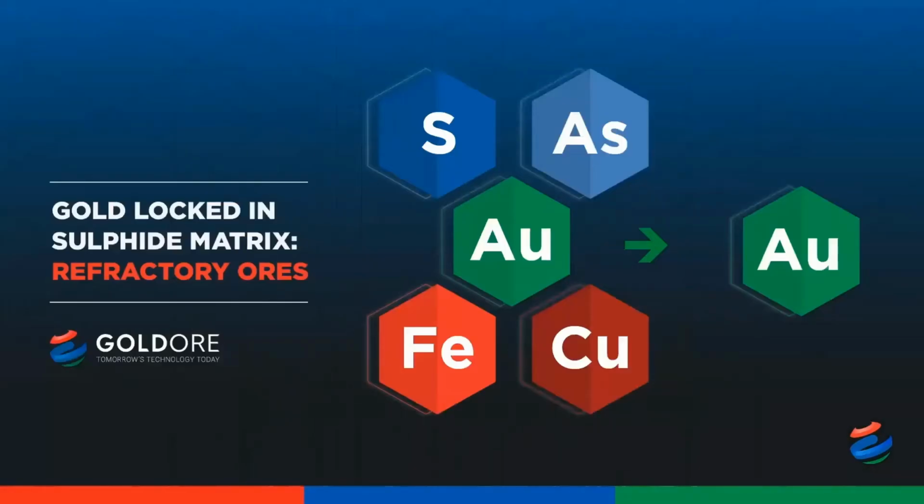By far the most impressive application of the Mach reactor in gold leaching is that of the improved recovery of semi-refractory ore bodies. GoldOre has a couple of applications of the Mach reactor on semi-refractory ore bodies on full plant scale, where a partial breakdown of the sulfide matrix is achieved in a very aggressive pre-oxidation at high Mach passes with oxygen and lime addition.